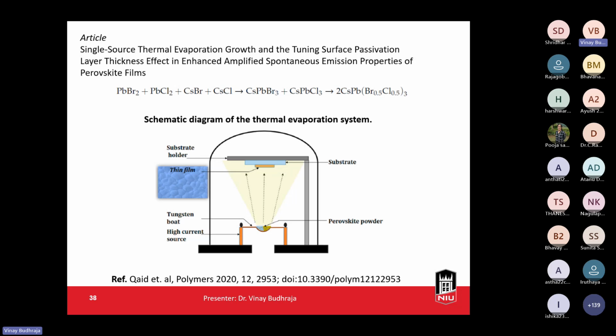This group tried to create the perovskite film, which is the final combination of CsPbBr0.5Cl0.5 to the 3, starting from perovskite powder, and used it in perovskite solar cells. Here's a substrate holder on the top, and then the boat is used. It contains the perovskite powder, and this goes through the high current source. When high current is applied at the bottom, the boat is made of tungsten, and the thin film grows on the substrate, with a combination of CsPbBr0.5Cl0.5 to the 3.